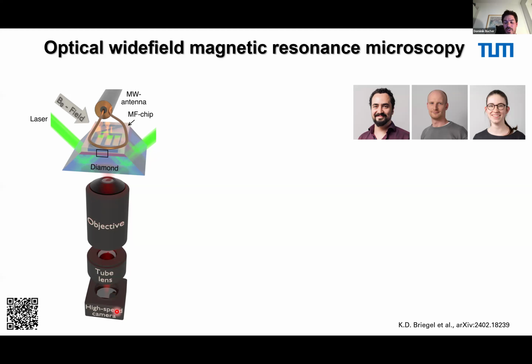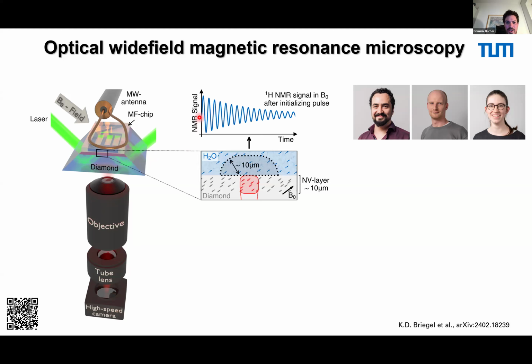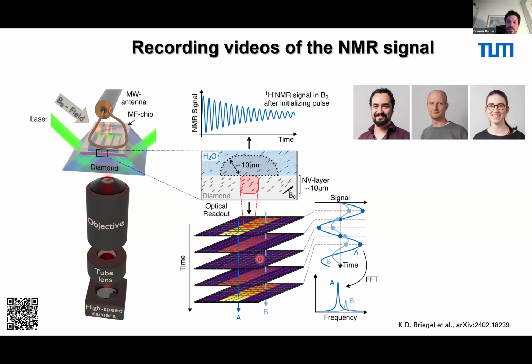At the end, it's not, because what we have to do is get this NMR signal, which is this free induction decay, which is then translated by the NV centers into a magnetic signal. And we have to make a movie of this free induction decay. So what happens is this NV center here translates this NMR signal into an optical signal, which is then basically oscillating in the time domain. And that's very distinct from the previous quantum diamond microscopes, where typically you don't have to get time resolved data. But if you do this NMR detection, what we do here with our approach, you have to take a movie of your NMR signal over time. So what you need here is a high-speed camera to take very fast images. And then you see, over the time trace, you will get basically your free induction decay for each of these pixels. And then you can take the Fourier transformation like a normal NMR to get your spectra.